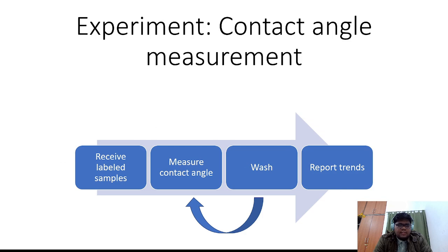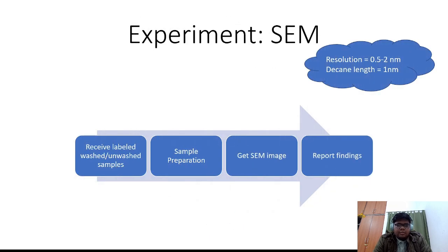Contact angle measurement: receive labeled samples, measure contact angle, wash, and then again measure contact angle. Do this several times to get some trends on how our new hydrophobic substance is performing under the ASTM standards of washing. Next, we will have to take some SEM images. So receive labeled, washed and unwashed samples, sample preparation, get SEM images and then report findings. It is good to know that resolution of SEM is 0.5 to 2 nanometers and decane length will be of 1 nanometer.